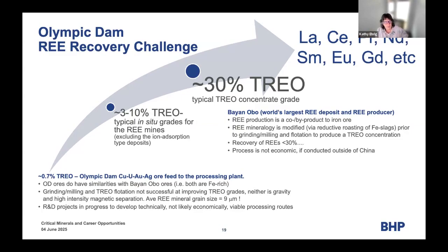Now, a couple things that I have on here. So where are we on that curve? We come way down at the bottom. Olympic Dam's feed is 0.7%. Our ores have similarity to Bayan Obo ores in that they're both iron rich. Grinding, milling, and total rare earth oxide flotation has not been successful at improving the total rare earth oxide grades for Olympic Dam material, and neither has gravity and magnetic separation. We could throw high intensity in there. Average grain size is 9 microns. We have R&D projects in place to develop whether it's technically viable, but not necessarily economic.